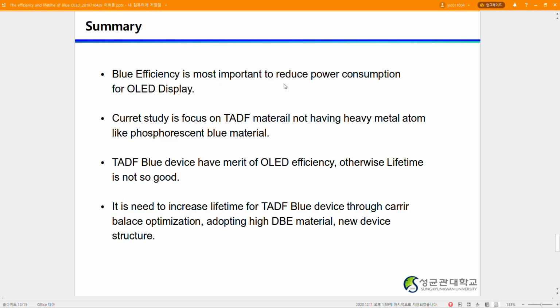In summary, blue efficiency is the most important to reduce power consumption for OLED display. Current study is focused on TADF materials, not having heavy atoms like phosphorescence blue material. TADF blue devices have a merit of OLED efficiency, otherwise, lifetime is not so good. It is needed to increase lifetime for TADF blue devices through carrier balance optimization, adopting the high bond dissociation energy material, and new device structure.